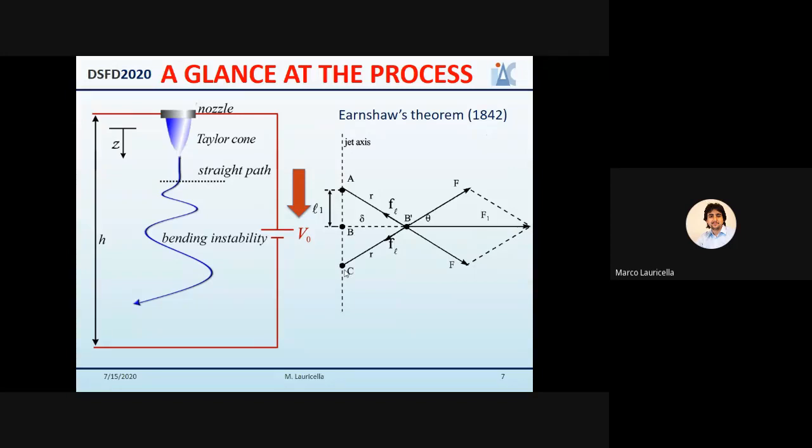The jet radius decreases under the effects of the stretching force. As a consequence, the longitudinal stress also decreases due to the smaller cross-section area of the jet. Hence, we observe the presence of the bending instabilities.